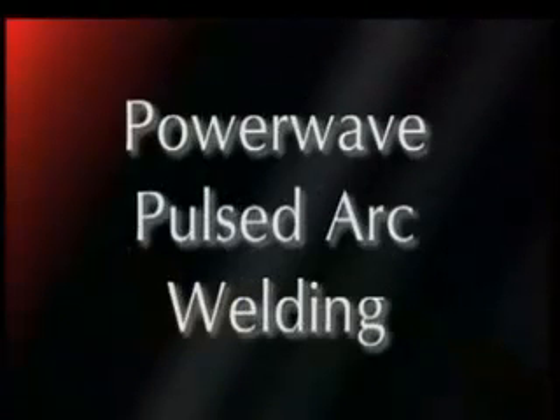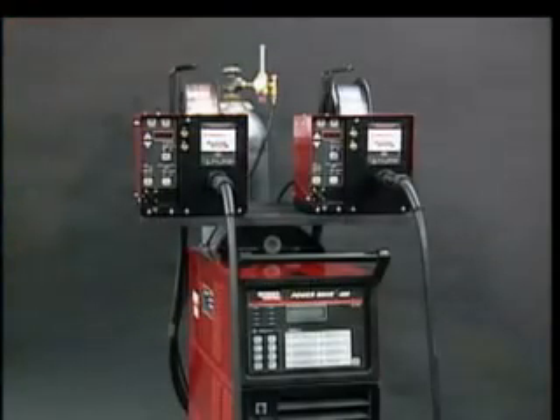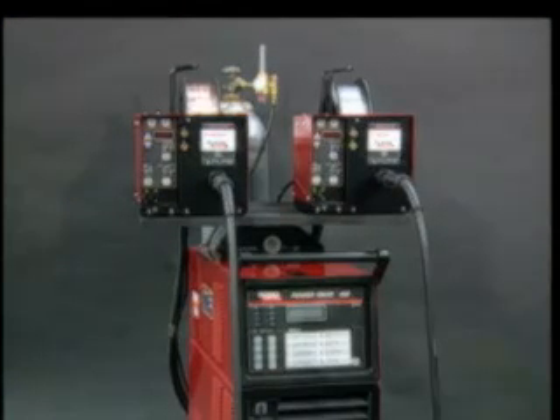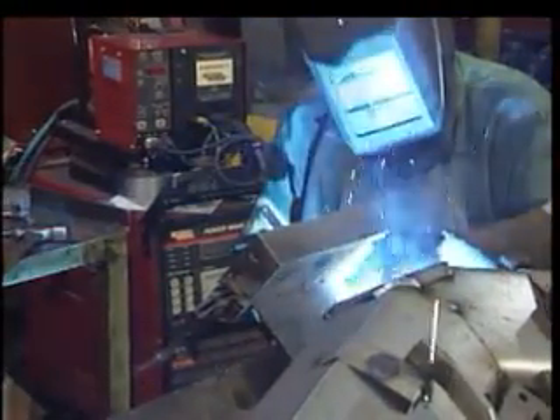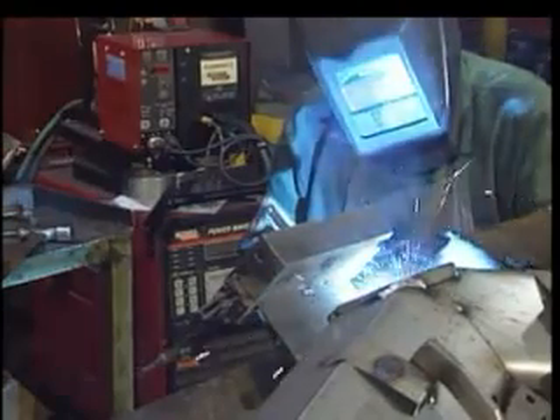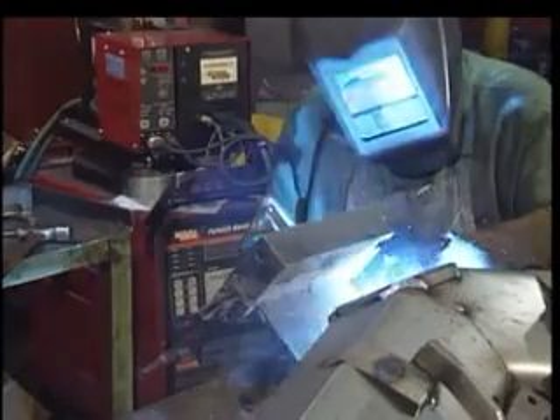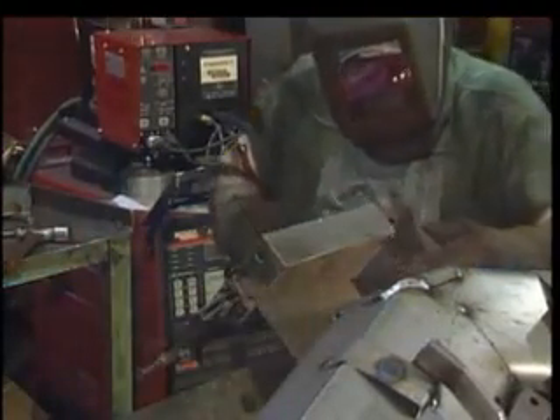Now, what if we applied waveform control logic to more than just short arc MIG? We would have precise control of the arc through a very broad wire feed speed range. That is the major benefit of using the Lincoln PowerWave pulsed arc welding process. The process allows wire feed speeds ranging from 50 to 1200 inches per minute, and it's virtually spatter-free across the entire range. With precise control of arc dynamics, the PowerWave can be used as a fast follow process at high travel speeds, or it can be run as a high deposition rate fast fill process.